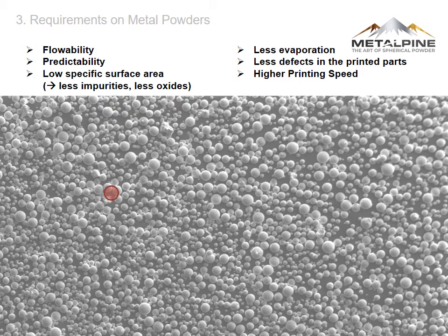So requirements on the metal powders are above all a good flowability, a good predictability of the process, and a really low specific surface area to decrease the number of impurities and oxides. So you can have less evaporation and less defects in the printed parts, and better powder quality also leads to a higher printing speed in the end.